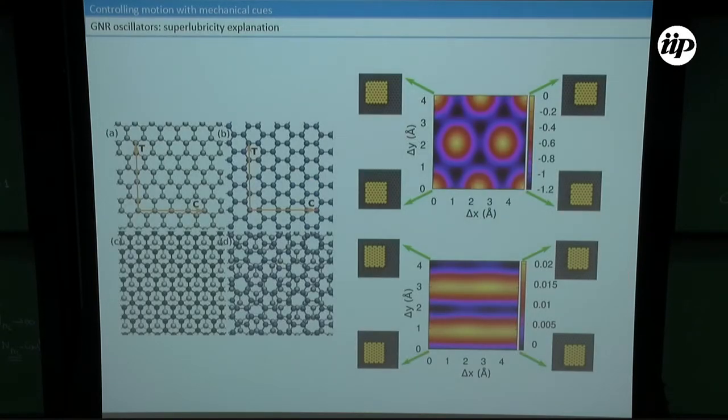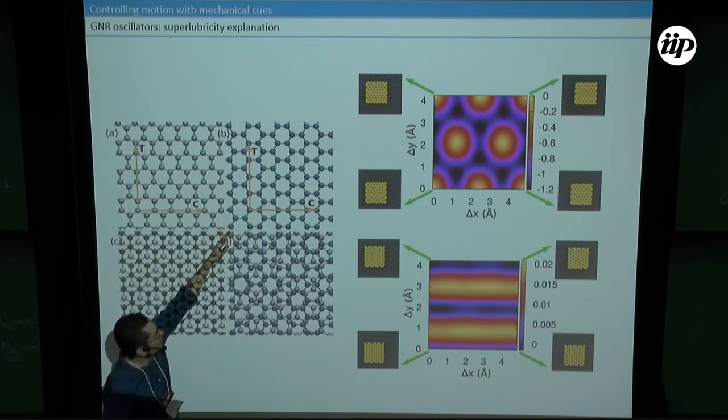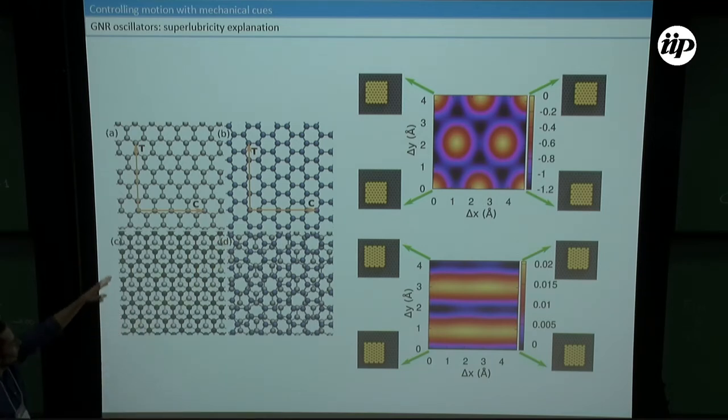And the idea is basically this one. I'm using two graphene sheets here. The one on top has some orientation. The second one has been rotated by maybe 30 or 90 degrees, so you can get from here to here. If I'm stacking two of those layers on top of each other, this is what they call the commensurate orientation. And you can see that there's a clear ordering here. For example, here this is the least energy ordering. That is the AB stacking.